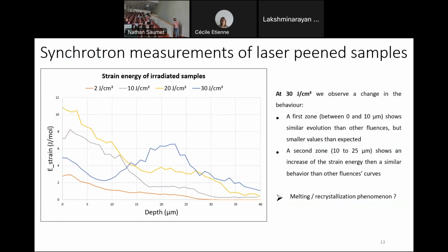And here I added a 4th curve, which shows a different regime, let's say, at very high fluence. We can see that the behavior is not the same as for the other ones. There's a second zone here, which appears with higher values of stored energy. So this could come from a melting and recrystallization phenomenon, which occurs just below the surface, and which, in a way, erases the effect of the shock wave. This is currently under investigation.